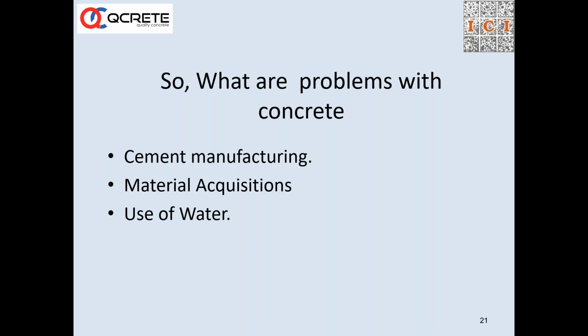And the next point is the OPC. As we are manufacturing, it generates about 800 to 900 kg of CO2 per ton of cement manufactured. And then OPC is the one material which is a synthetic product in the concrete, and it tends to go back to its natural state. So limiting the OPC is prudent and important because in that way you are increasing the stable components of concrete.